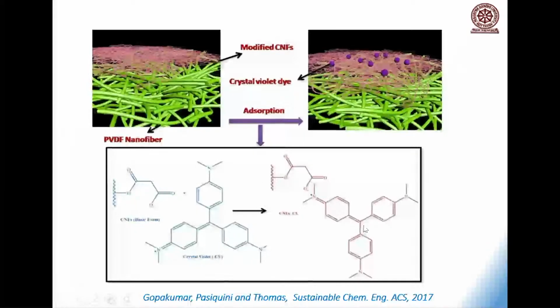Crystal violet can interact with the nanocellulose by electrostatic interaction. You see the CO minus and the N plus. Because of the electrostatic interaction, you can see all the crystal violet molecules have been adsorbed on the surface of the chemically modified nanocellulose. Those who are interested can look at our publication, the ACS.